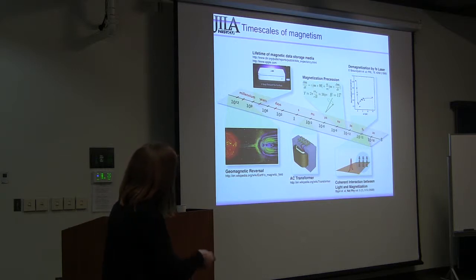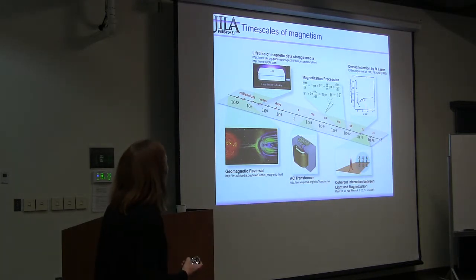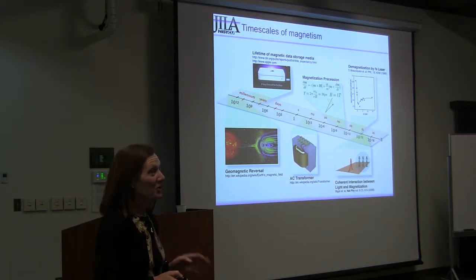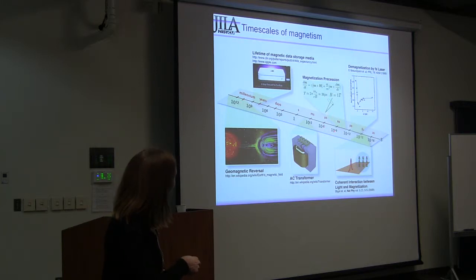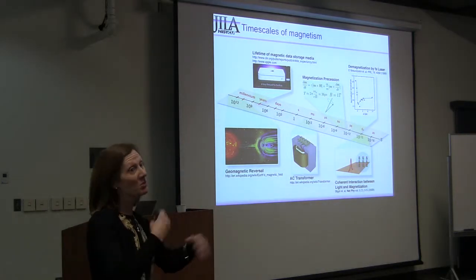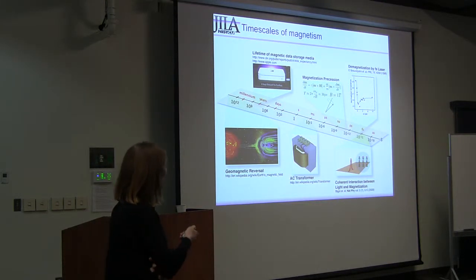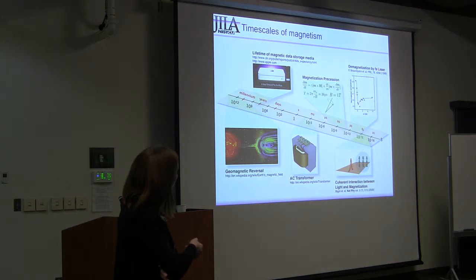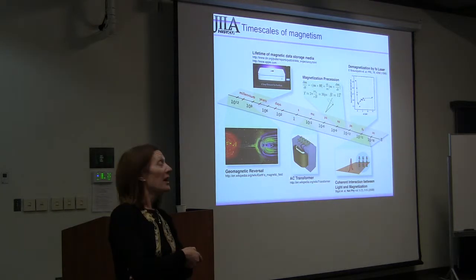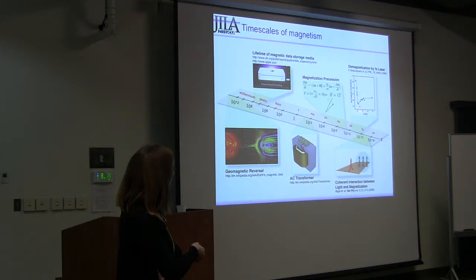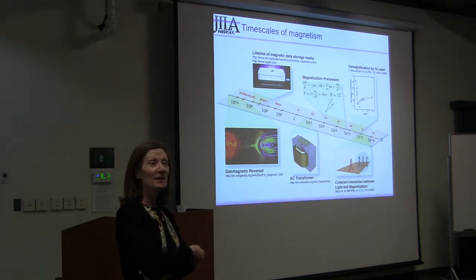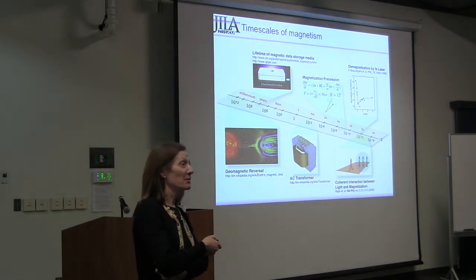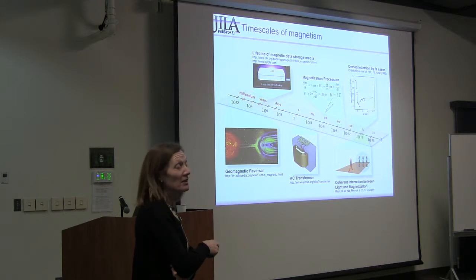So, just as a brief introduction to the work, the timescales of magnetism span from the very long, but for a long time it was not understood that they also span to very short timescales, because people thought that the fastest timescales were on the order of nanoseconds, which are the precessional motion of the magnetic moment. But then, just about 20 years ago, Jean-Yves Bigot's group did an experiment where they shone a femtosecond laser on a magnetic material, and the material demagnetized, you can see it, this is 5 picoseconds, so it demagnetizes in about 100 femtoseconds. It was a big surprise to everybody, because that can't be explained by a precessional motion. That's way too slow.